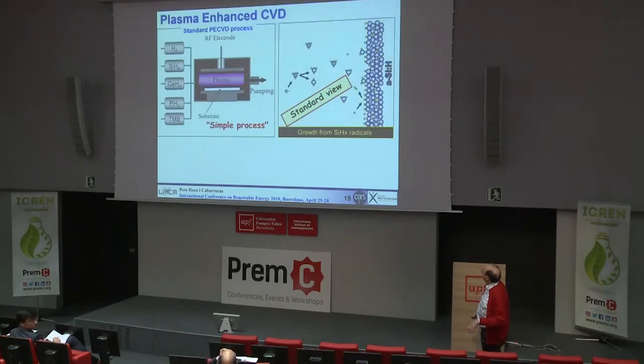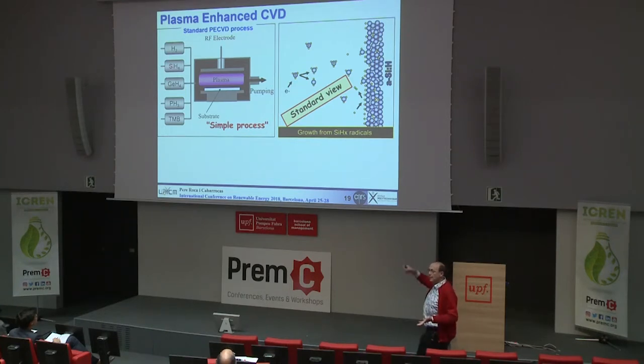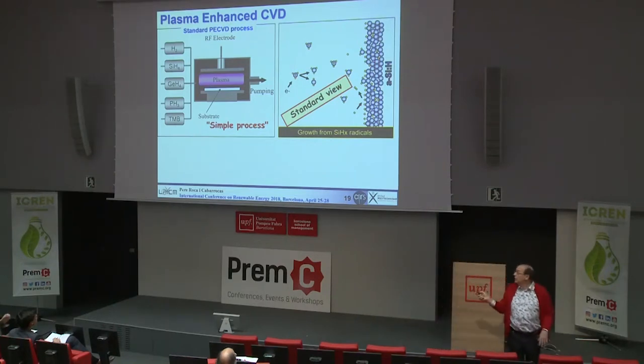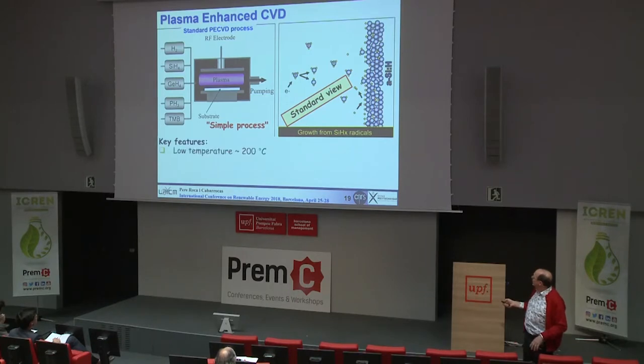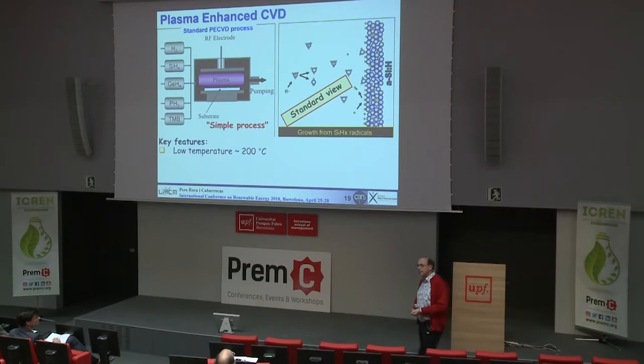So amorphous silicon, standard process: you have gases, silane, the starting point for the whole crystalline silicon technology. Those gases we put in a plasma CVD reactor, you put power, you turn on the light, you start to deposit things, and normally, if you are at low temperature, 200 degrees, what you obtain is a disordered material. So it's wonderful, but it's disordered, and if it's disordered, you have defects, and if you have defects, you have recombination, and you have lower efficiency devices. We will see the efficiency.